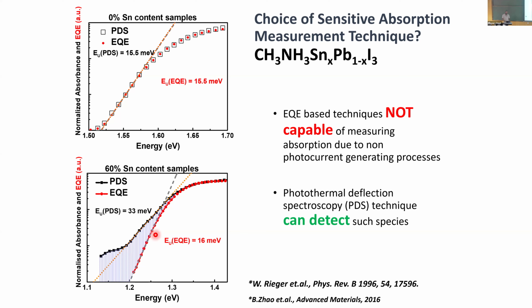So anyways, the point is doping, and for people who work on semiconductors, this doping acts as a trap. If you talk about transport, that is not a desired feature. But if you want to talk about disorder or Urbach energy, it should include that, because that actually is a factor that reflects disorder. Many papers don't include this, and I have pointed this out to others who are placed very well, and they have acknowledged that. When you measure the disorder using photocurrent, you should explicitly mention that you have done this using photocurrent, which doesn't measure the contribution of doping. That is okay. The material is excellent because the disorder is low, but the device,